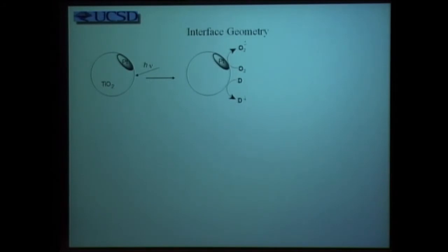Chemistry then follows it as a function of that. Now suppose on the second line, instead of having titanium exposed for most of the particle, you had the metal platinum at the center of a semiconductor and titanium dioxide completely surrounding it. Under those circumstances, you'll get the same reactivity because the photon will be absorbed by TiO2. Platinum will be used as an island to trap the electron, but you'll undergo oxidation from a donor to acceptor.